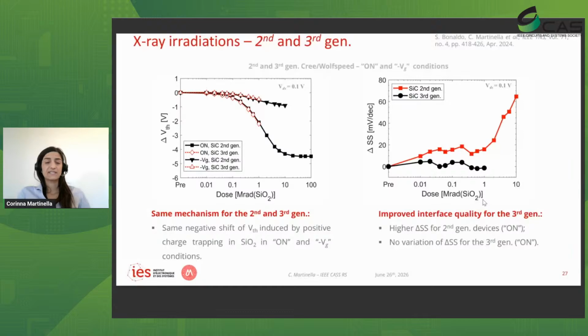We also compared results from devices of different generations. We used Wolfspeed devices from second and third generations. When we look at the degradation of the threshold voltage, the threshold voltage shift, we are plotting results as a function of the dose, and we see exactly the same mechanism between the second and third generation, meaning that there is no difference in the mechanism that is happening there. So we are trapping positive charges in stable defects in the oxide.